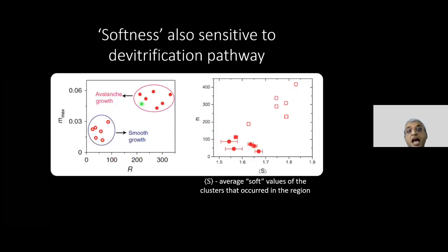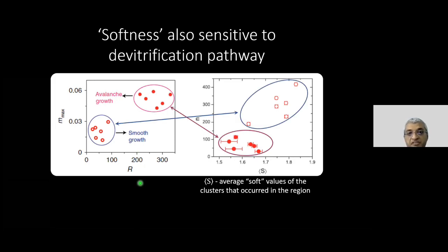Right, and we also found that softness cannot just tell you where it grows. You might recall that I told you we found 2 different pathways for the devitrification process. We call them the avalanche and the smooth growth process, and if you were to correlate it with the softness and the number of times the soft particles appeared there, you find that once again you see 2 clusters. So softness not only predicts where crystals will grow, but also tells you how they are going to grow.